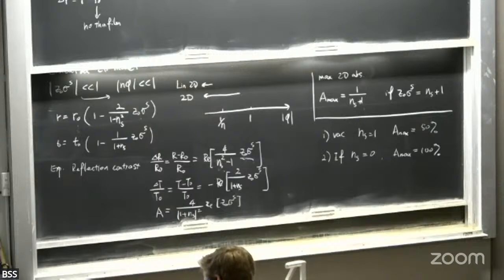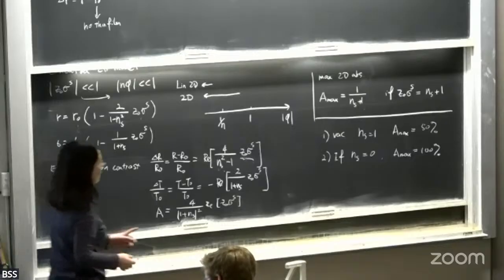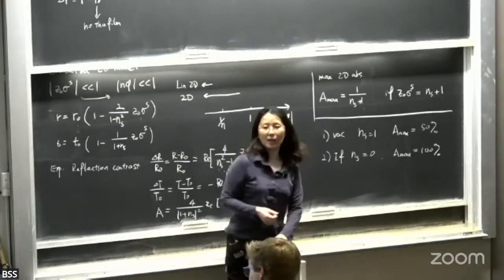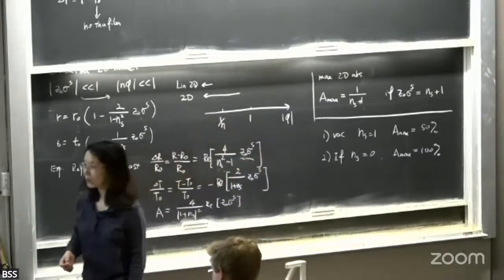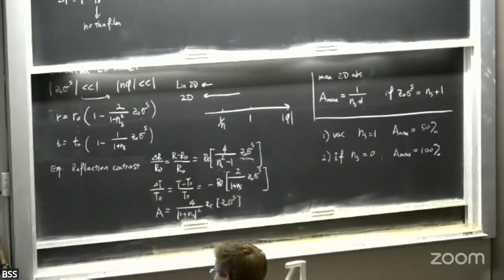Everything is absorbed, 100%. So how do we do this? The idea is that if you have a perfect conductor, a perfect mirror, and then you put your sample at a quarter wavelength away from your mirror, the effective index for your substrate, mirror plus this vacuum or whatever in between, gives you an effective index of 0, okay?